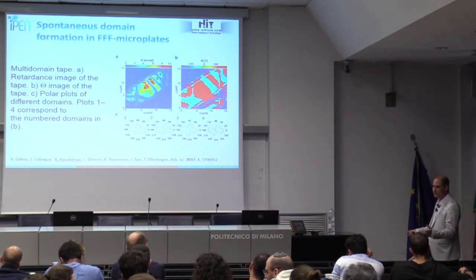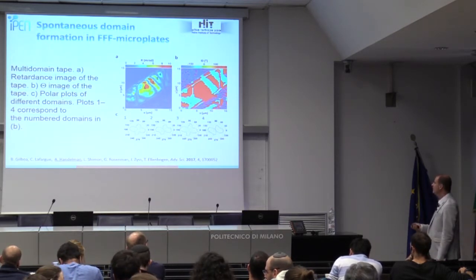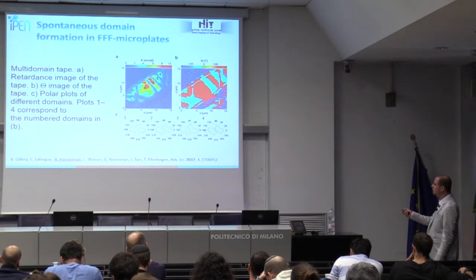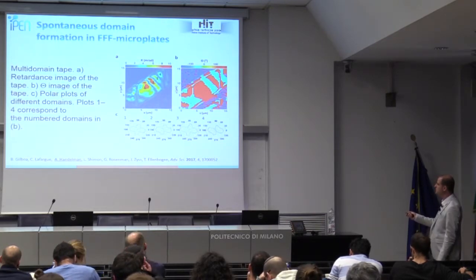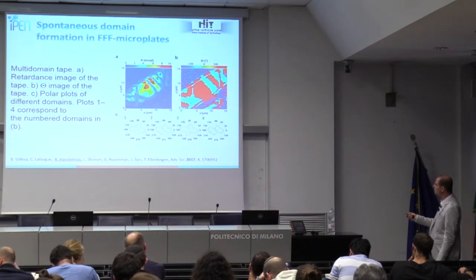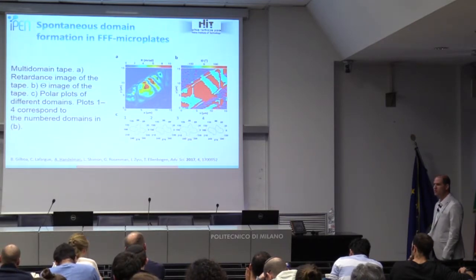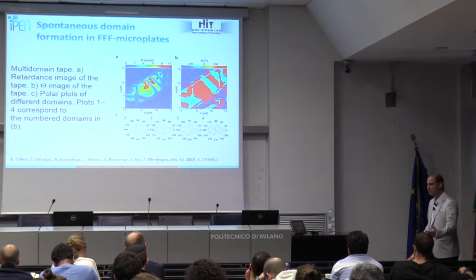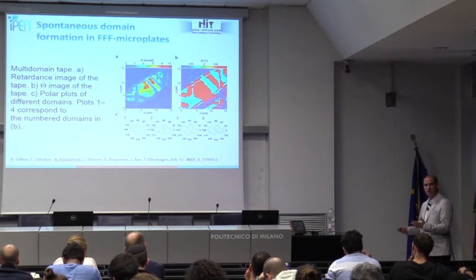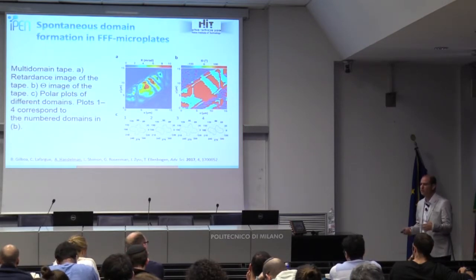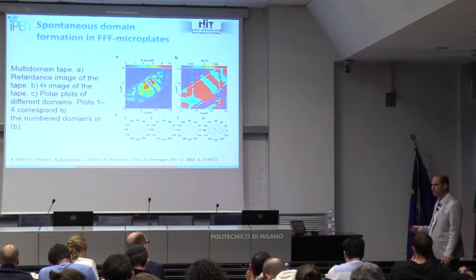So we published it, of course. And we see that domain 1 and 3, you see here the polar points are very similar. And 2 and 4 are also common. So we can use them to engineer our peptides for all kinds of ferroelectric, or not ferroelectric, all kinds of polarization and domains.